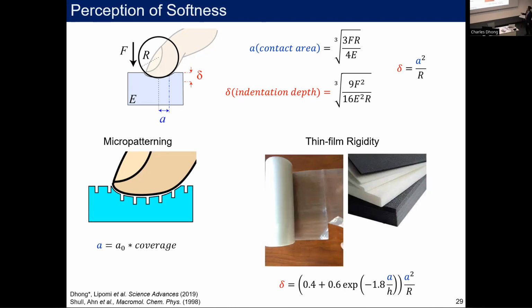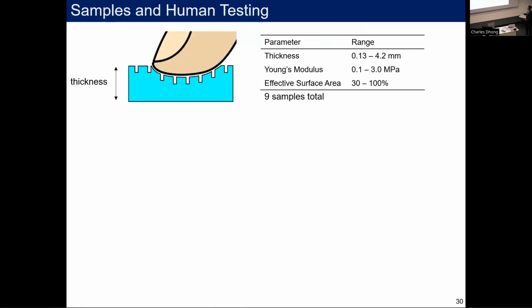The other thing is this thin film rigidity. If you make a very thin film, then it appears to be much stiffer than its bulk counterpart because, right, you're building up that gradient at a much smaller thickness. The significant part of this for us is that now you have this thickness dependent, H, relationship between indentation depth and contact area. So using these two tricks, we can create a lot of different samples that vary in their thickness, their Young's modulus, and their effective surface area.